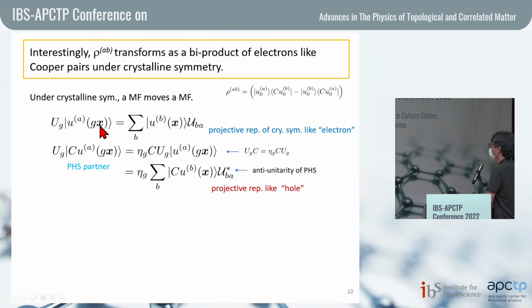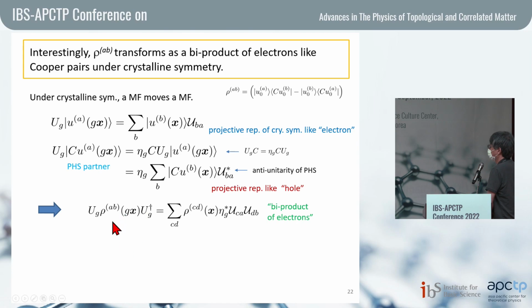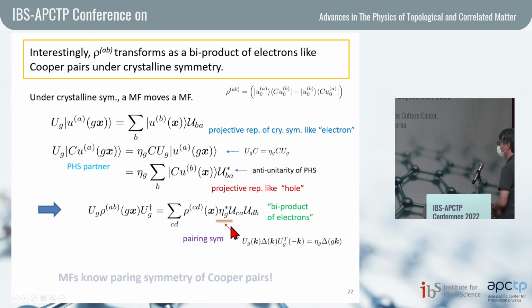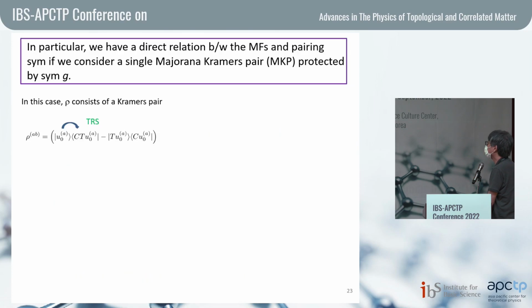So finally, by using these two relations, we can obtain the transformation law for the rho operators. So if you calculate these relations, then we have this one. So now we have a complex conjugation here. So the complex conjugation comes back to the original one. So that we have these relations. And so this means that the rho transforms like a bilinear of electrons, like Cooper pairs. And we also have this non-trivial factor here. And this comes from the pair symmetries. So this means that Majorana fermions know the pair symmetry of the Cooper pairs.